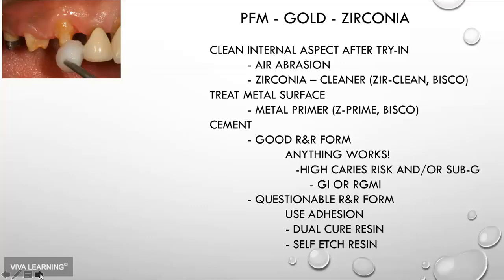Well documented and well proven with recent research. So I know we were told otherwise earlier in zirconia's history, but I can tell you now, absolutely, you can and should use air abrasion on the internal aspect of a zirconia restoration. So after we've air abraded, now I go back, and whether it's PFM, gold or zirconia, I'm going to clean out the inside with the ZirClean material, because I may not have got 100% of the internal aspect of that crown cleaned with the air abrasion, but I know with the liquid aspect of ZirClean, I will 100% cover all the surface area and get rid of all contamination.